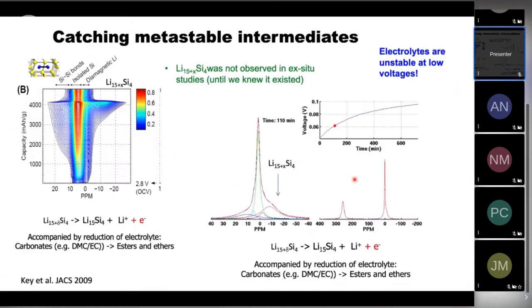But actually, we were one of the first to use our in-situ NMR methodology to really understand what was going on. And so this is our in-situ NMR showing lithiation. When you lithiate this material, you form a series of silicon clusters. So here's one cluster, for example, containing silicon-silicon dumbbells. It gives rise to these peaks at positive ppm. And then we saw this new environment, Li15Si4, which we never saw when we did ex-situ measurements. And it turned out that it was an environment where extra lithium is inserted into this material.